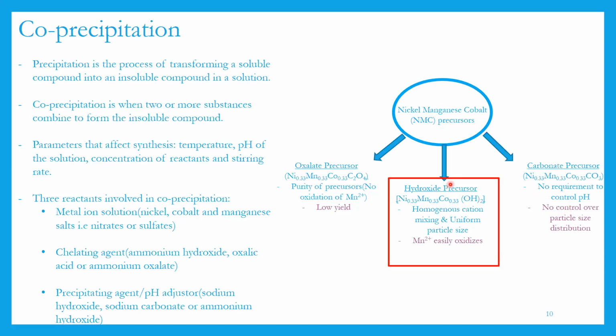The work that I'll be talking about, which was recently published, focuses on hydroxide co-precipitation. Normally in hydroxide co-precipitation, you have three main reactants. You have the metal ion solution, which is mostly metal ion sulfates. The chelating agent we use is ammonium hydroxide, but ammonium hydroxide easily volatilizes into ammonia gas, and it's very toxic. So I looked at a different method, where you use lower concentrations of this chelating agent, and then used a theoretical model to optimize that synthesis.